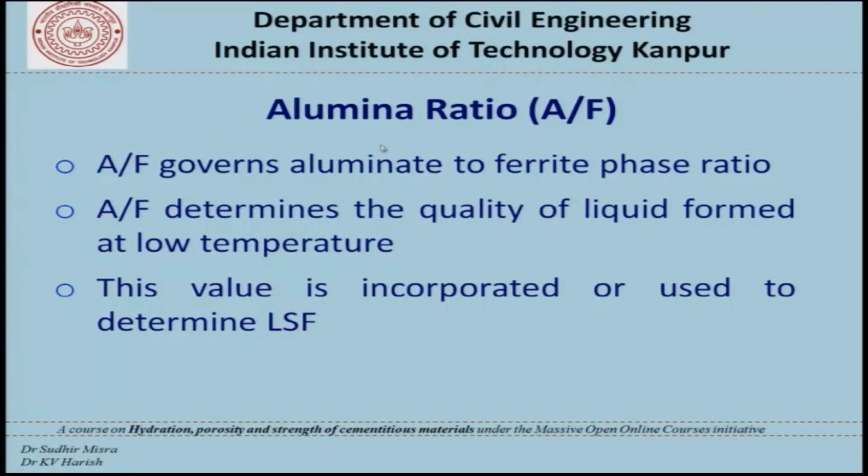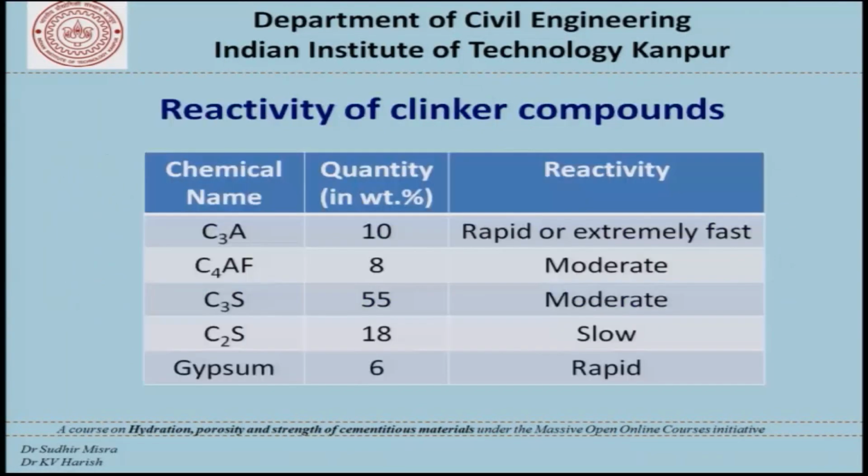The third important factor is alumina ratio, A by F, and this governs primarily the aluminate to ferrite phase ratio, and this determines the quality of liquid formed at low temperature. This value is also used to determine LSF.